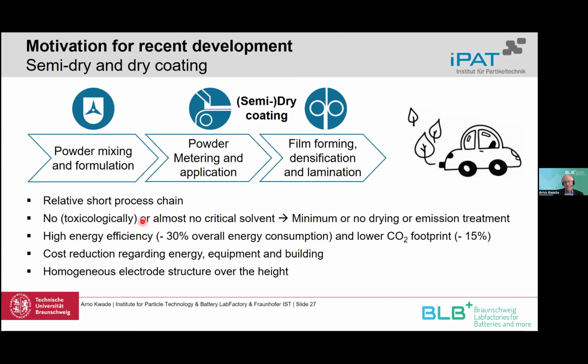We can also avoid critical solvents, because, for example, for the cathode material we need NMP as a solvent to work with PVDF as a binder. We have a much higher energy efficiency, minus 30% of the overall energy consumption. You have seen 40% was for coating and drying, but now we need only 10% instead of 40. And the CO2 footprint is also getting much better. We have a cost reduction, and the buildings can be much smaller.